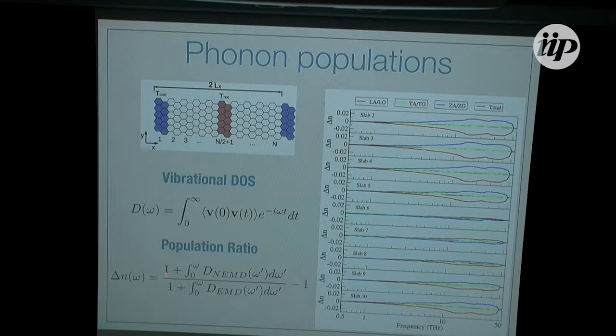So what we did was to use this vibrational density of states to define a population ratio between non-equilibrium simulations and equilibrium simulations, right? These factors of 1 here are just to normalize this such that if this delta n is smaller than 0, you have a decrease in phonon population. If it's larger than 0, you have an increase in phonon populations. And then we calculate this change in phonon populations at several different parts of the system. And then what we see is that clearly you have perturbations, particularly in the longitudinal acoustic mode and the flexural acoustic modes, right?